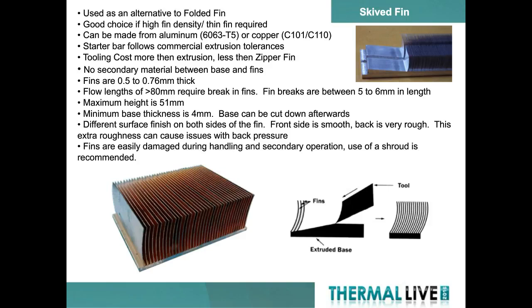One point of note is that because of the way the fins are formed, one side of the fin is going to be extremely smooth. The opposite side of the fin is going to be extremely rough. This can be problematic when people start looking at how much pressure drop there is, or if they're worried about a high dust environment. It's very easy for the system to actually act as a dust collector if there's not a filter someplace in the system.